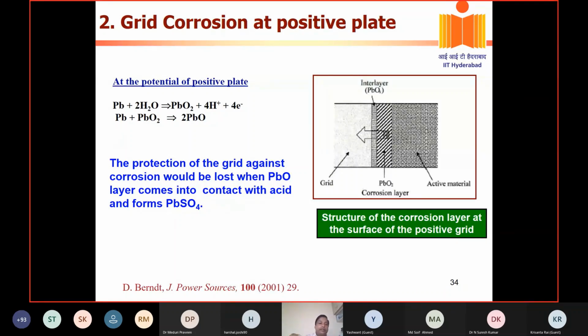But remember, at the positive, lead dioxide is the active material. So when you are coating PbO2, Pb and PbO2 don't exist together for thermodynamic reasons. If they existed together, the voltage would be zero, right? So there exists an intermediate PbO layer between the grid and the active material. That is called grid corrosion. If this layer comes into contact with acid, it will form PbSO4. Then it will lose, and the issues will start.